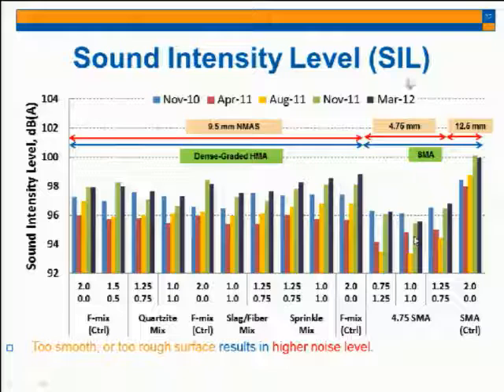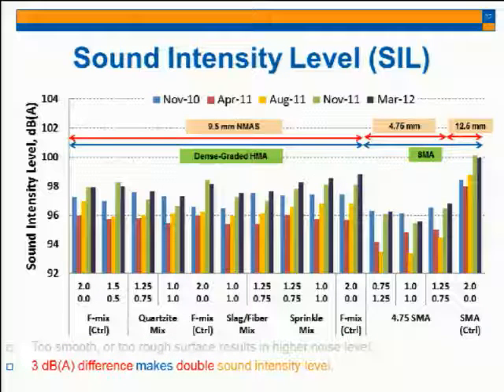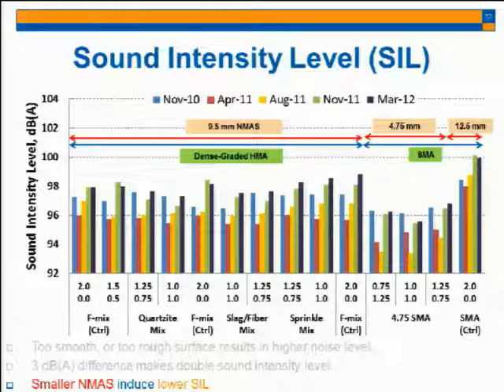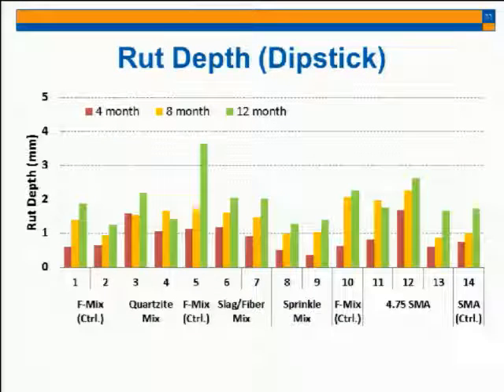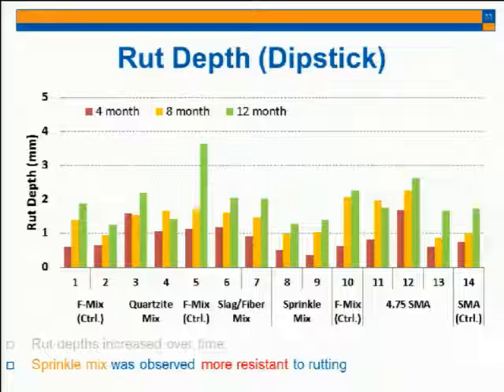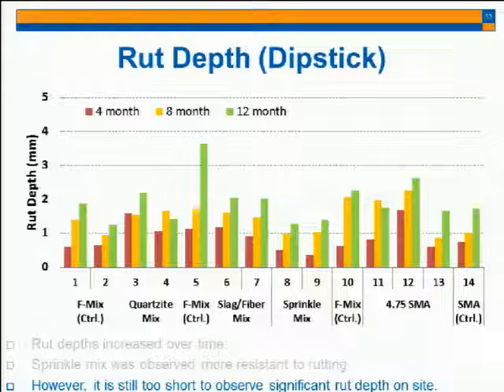As you can see here, it is largely dependent on the aggregate size. The 4.75 SMA mixture provides a very low sound intensity level, while the 12.5 SMA mixture provides the highest sound intensity level. Usually a 3 decibel difference means double the sound intensity level. So, rut depth. For rut depth, one year is still too short to observe significant rut depth in the field. So we will see more data.